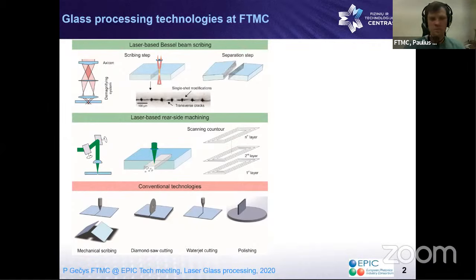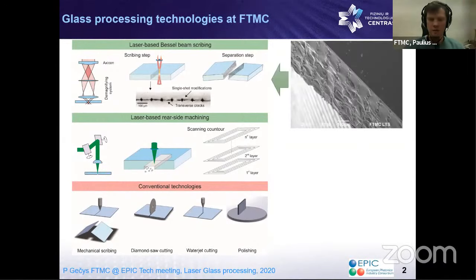As for Bessel beam dicing or scribing, we already heard some talk. Basically here you need to perform some elongated modifications inside the glass along your desired cutting path, and then you apply some mechanical load to separate your samples. This is a really fast technique in terms of dicing speed. But it also has some disadvantages. For example, it can be applied only to low curvature cutting contours. That means you cannot really cut narrow holes and so on.